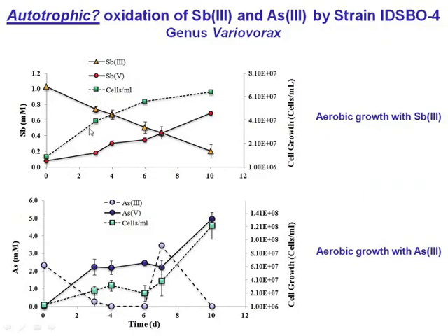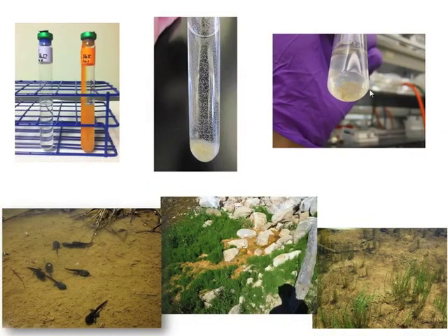But you'll notice we get decent recovery of antimony 3, but not complete recovery. And my student who is growing this bug again has shown that some amount of the antimony 5 that's being produced in this case is ending up as the mineral mopungite, okay, as an insoluble precipitate during microbial cycling. Okay, so we see lots of precipitation, both oxidation and reduction of antimony 5 and 3, coupled to autotrophy, coupled to heterotrophy, driving the precipitation of either stibnite mineral or mopungite or senarmontite, primarily.